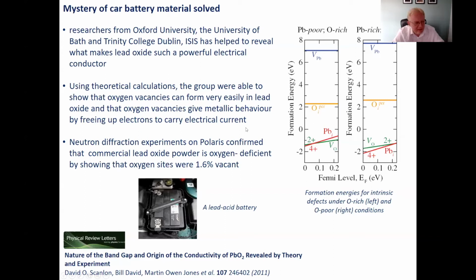Their theoretical studies showed that if you had this number of vacancies, then you would have this certain amount of current. But they wanted to count the number of oxygens present in the material and see if it correlated with their theoretical measure that they'd derived from the measured conductivity of these samples. So they gave us samples of lead oxide. Now, of course, because we're not dependent on atomic number, our scattering from oxygen is just as good as our scattering from lead. And so we were able to see very closely and very precisely the amount of oxygen within the PbO, or PbO(1-x).